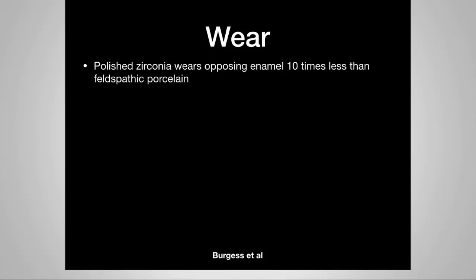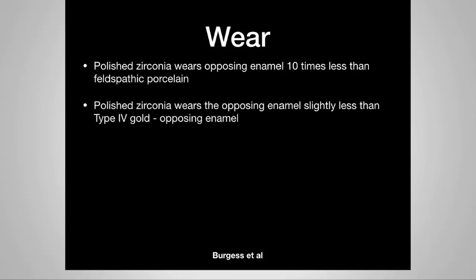Polished zirconia wears opposing enamel 10 times less than feldspathic porcelains. Feldspathic porcelain, remember, is basically all of our PFMs. So if it's polished, we're going to get 10 times less wear than our traditional PFMs. Polished zirconia wears the opposing enamel slightly less than type 4 gold, so that's something you can certainly compare it to.